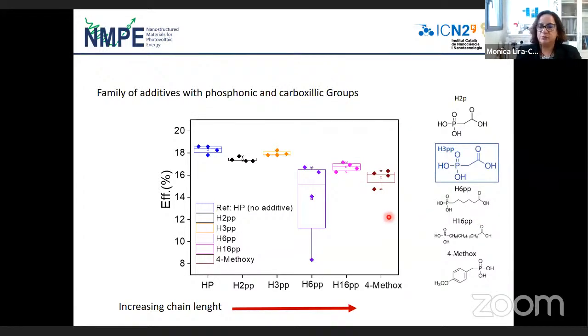And what we did, we analyzed the family, increasing the chain length of the alkyl group. Here you have the reference devices, with chain length increasing in this way. You can see that we were not able to increase efficiency because the voltage was always below or only similar to that of this molecule, which has 3 carbon groups.